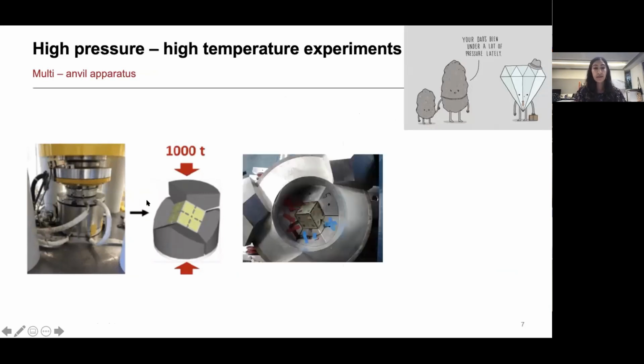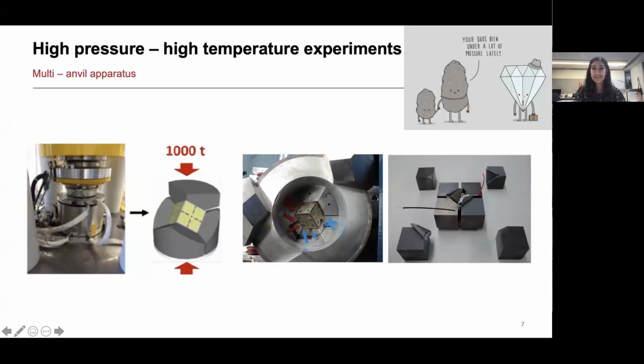The interior of this multi-anvil apparatus looks like this, top view down. And here we can see anvils. These are called first stage anvils. And these can apply a force onto a cubic geometry. And inside of the cubic geometry is my experiment. So it's a bit like Russian dolls. It gets smaller and smaller the further inside that you go. Contained within this octahedra is a sample which is only 1.5 to 3 millimeters long. And that's where I can pack small amounts of rock powder.